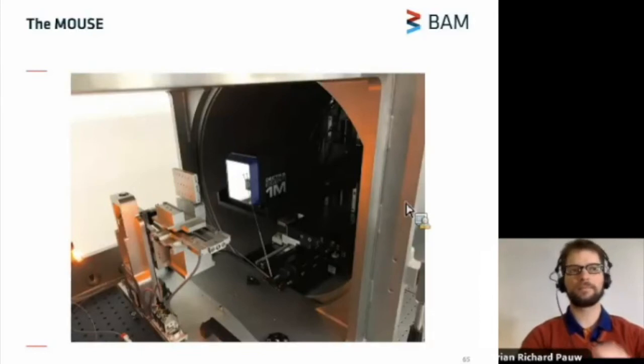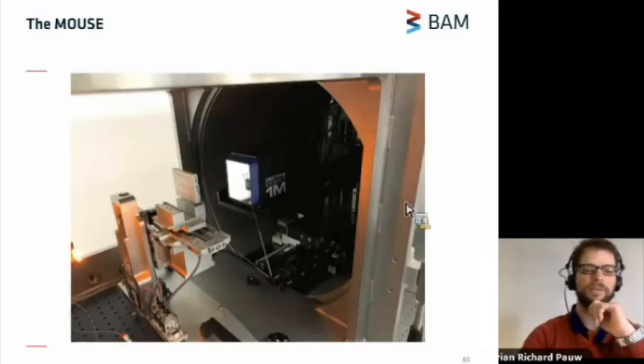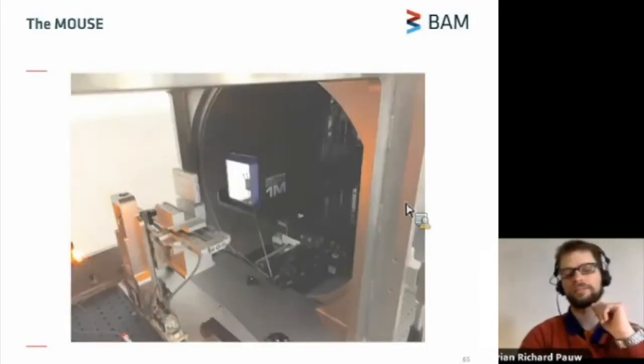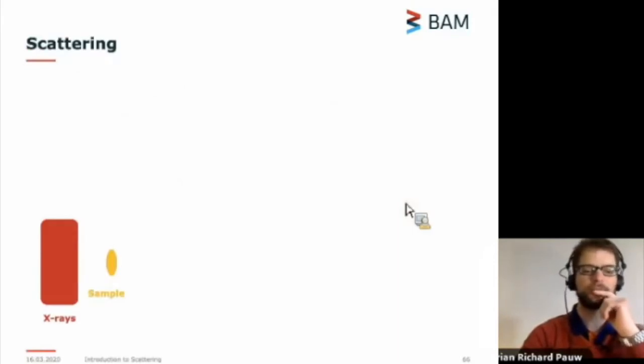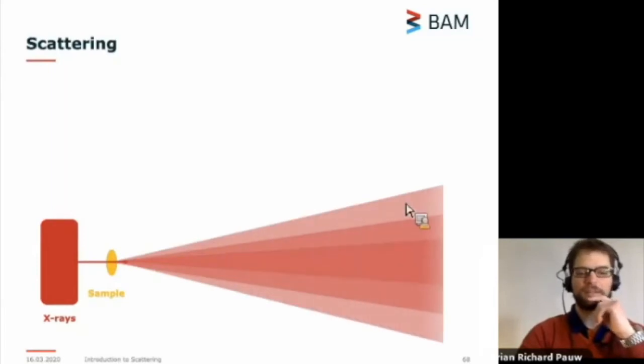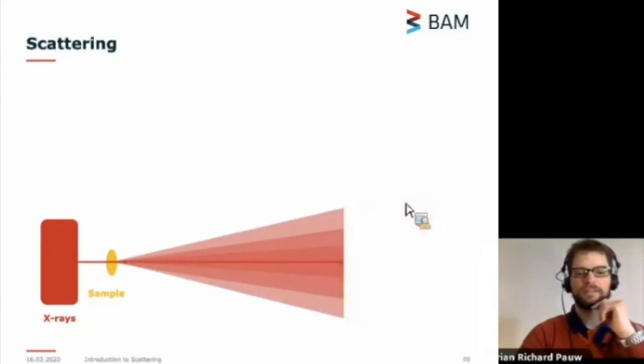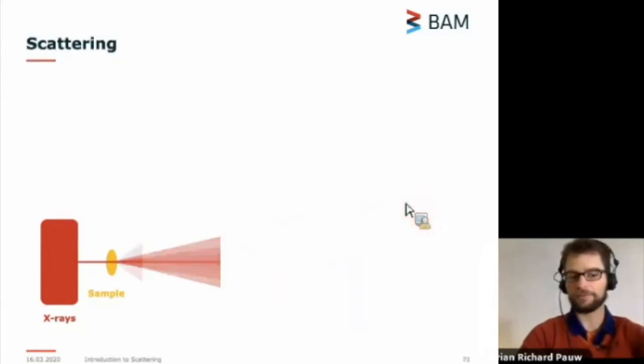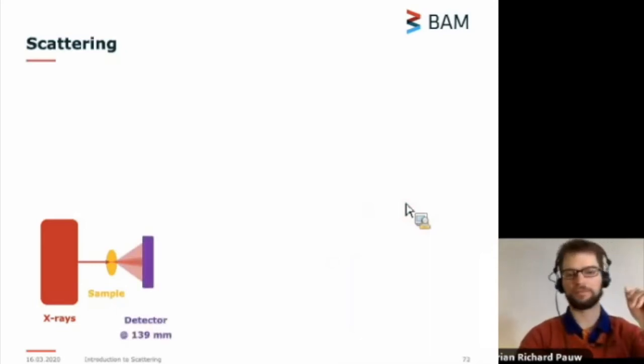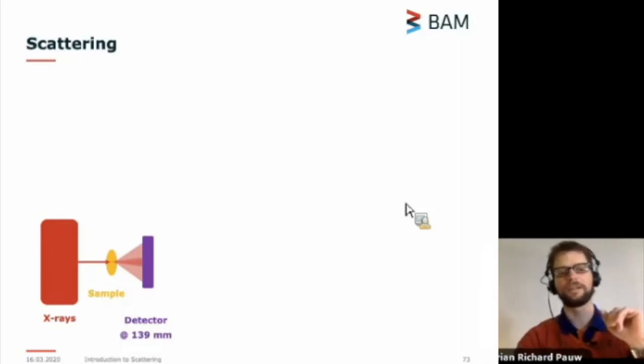So that means that when we have our schematic description of our experiment, we measure each sample first with a detector very close to the sample. Actually, we can move this much closer than this. We can move this about 1 centimeter from the sample. If we're not careful, we can actually move it into the sample. So it is a little bit risky to do this, but it has great benefits.